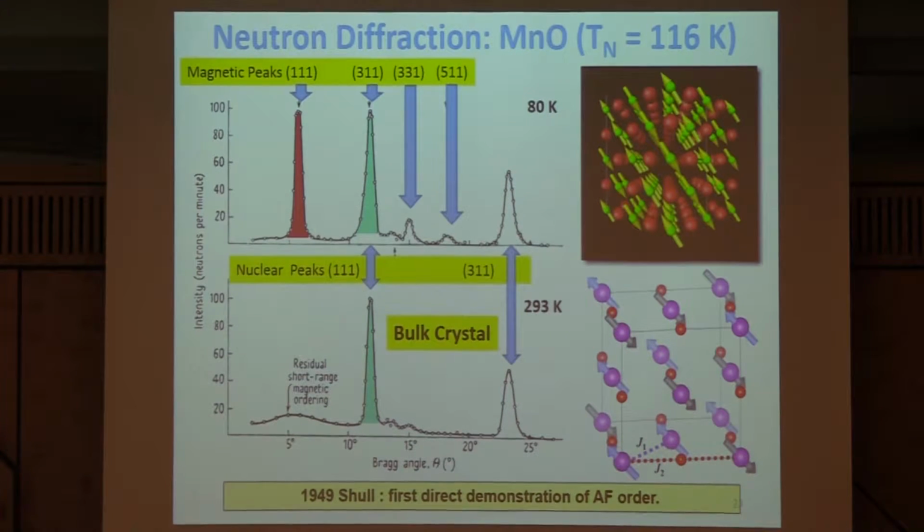It helps a lot if your transition temperature, this is diffraction from an antiferromagnetic material, which we're most interested in here. It really helps a lot if you can access a system where you can get reasonably well below and well above the Néel temperature to see the difference. So here's a material, Néel temperature about 120 Kelvin. Above, you see the structurally allowed peaks. Okay? So this is the unit cell. So there's a whole series of peaks which are allowed because of their particular unit cell basis.